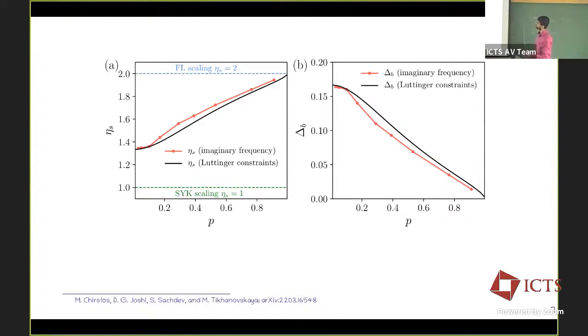So here, let me first show you the right plot. This is delta B as a function of P. And this black curve is exactly the analytic relation between delta B and P, and we have plotted it in this plot. The machinery that goes into getting this relation is again using the Luttinger relations, because those are the ones that depend on thetas and deltas, and you eliminate certain constants in this particular case, and you get an exact expression.